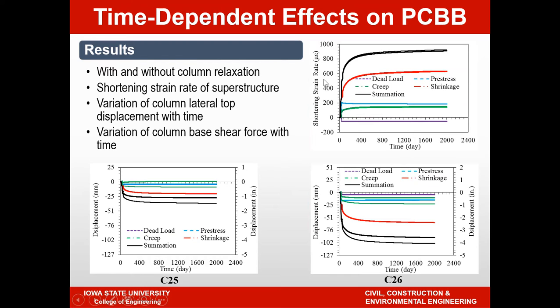Looking at a total shortening strain rate, in this case 900 plus microstrain is what you're expecting at the age of about 2,000 days. And all of our analyses were performed for time equals 0 to 2,000. The bottom two figures show the column displacement. The column displacement shows again dead load, creep, pre-stress, and shrinkage, as well as the summation. You also see two black lines, which show with and without the relaxation that the system will experience.